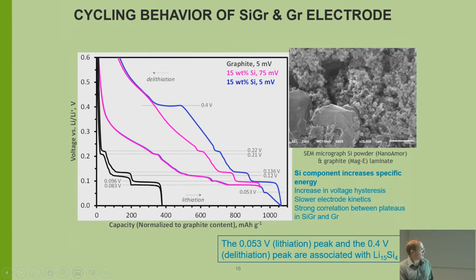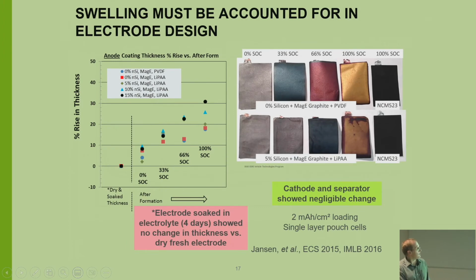I like to show this plot because it's the same silicon electrode, where here I have just 5% silicon with graphite. And as you add more silicon to your cell, it swells. You put lithium in silicon, it swells. And then that cracks your passivation layer, and then it reforms, and then next time you charge, it cracks again. So you always have a little bit of gassing issues and cycle life issues.